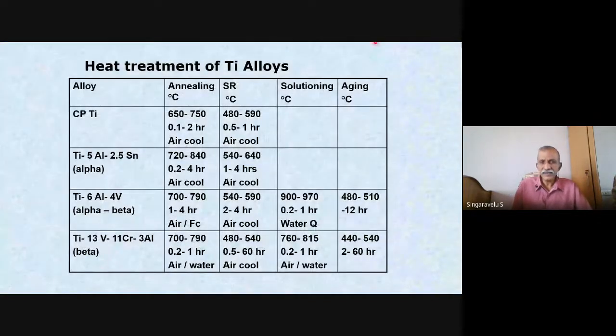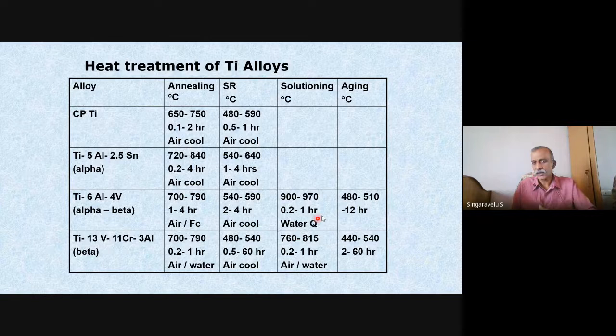These are various heat treatments, just for information. I said, solution treated and aged. You have to take it to 900 to 970 for alpha beta alloys and quench it in water. One hour, keep it and quench it in water. Then the strength becomes high. And if you do the aging after that, the specifications will come out. So the temperature becomes 480 to 510 for 12 hours. You see the aging treatment. Like that, for the beta alloys, the solutionizing treatment temperature is 760 to 815 and so on.